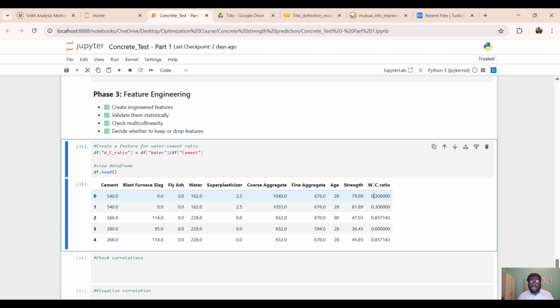So in this case, you see that the water to cement ratio is 0.3, something meaningful. But in here, look at this. This is so high. This is 0.85, a lot, okay? And then, I mean, it is understandable that the strength is this small, even though the age is 90. You can imagine this is 28 days. We have about 80 Newton per millimeter squared. And this is 90 days. Despite the fact that it is 90 days, we have this low strength. I mean, it is understandable from this water to cement ratio. That's just me judging, okay?